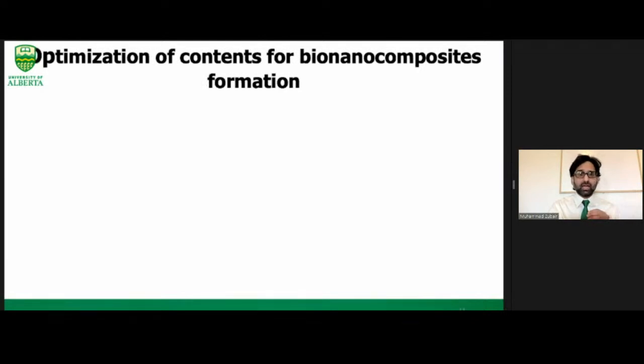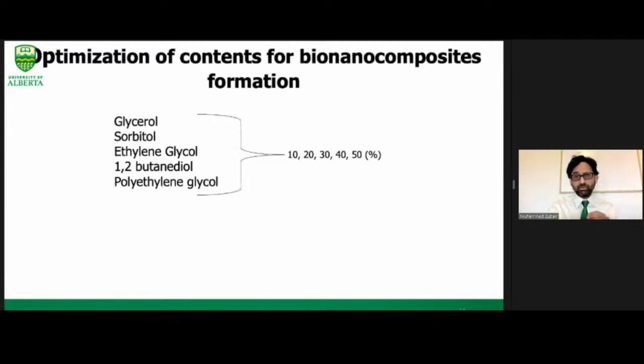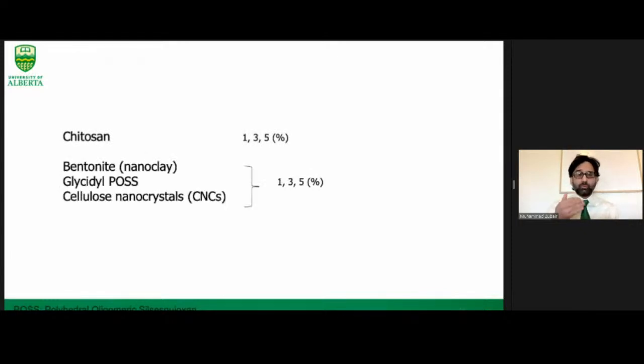Furthermore, these extracted proteins were transformed into food packaging films. For the conversion of these proteins into food packaging materials, different plasticizers were used: glycerol, sorbitol, ethylene glycol, 1,2-butanediol, and polyethylene glycol, at 10, 20, 30, 40, and 50%, to find their best concentration for developing protein-based food packaging materials. The water content was used between 10 to 20%. Furthermore, the cross-linking agent chitosan was used at 1, 3, and 5%. At the end, 3 different nanoparticles were tried to improve the physicochemical properties of these proteins: the first one is bentonite, the second one is glycidyl POSS, and then cellulose nanocrystals. These 3 nanoparticles were used at 3 different concentrations of 1, 3, and 5%.